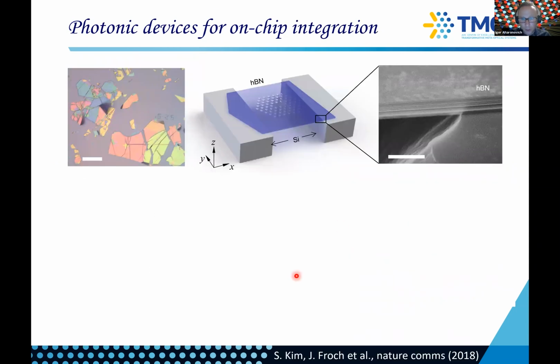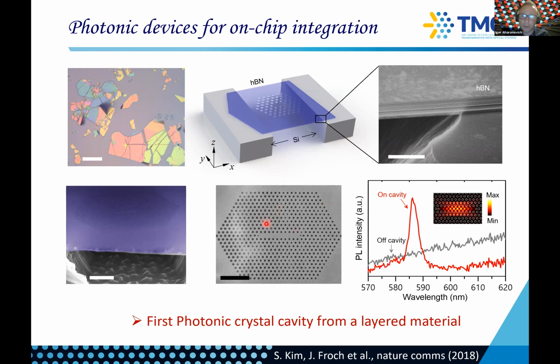We started this journey a few years ago, pioneered by Sejeong Kim and Johannes. Sejeong is now faculty at Melbourne University, and Johannes moved to a postdoc with Arka and Jiadong in Washington. What they did is first exfoliate a lot of hBN and calibrate our optical microscope to know the thickness of the hBN based on color, because there is no point in making devices if your thickness is off. They could exfoliate exactly down to the required thickness, which is a couple hundred nanometers. Then you can easily pattern it with normal reactive ion beam etching. The undercut is achieved simply by putting these devices on top of a grid.